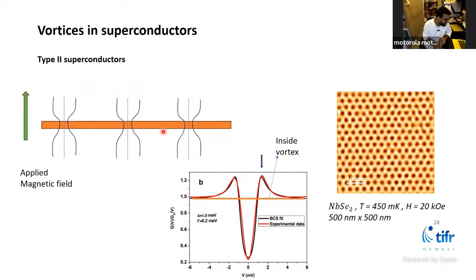For example, in the same niobium diselenide that I have shown you the atomic image of, you can see the formation of vortices at this 450 millikelvin sub-Kelvin temperature at an applied magnetic field of 20 kilo-oersted. Now this entire image is 500 by 500 nanometers. These are not your atoms, those atoms were in the sub-nanometer range. As you can see, there are probably 10 vortices in 500 nanometers. These are something different that actually acts as a soft matter system to study various things.